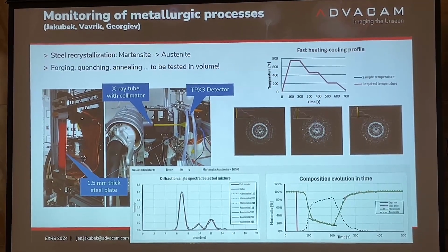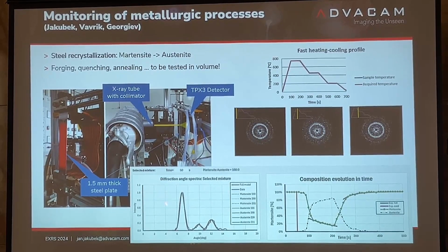One can prepare a very solid model for it, and here I am showing what happens. You know, this spectrum here. These are angles and intensity. These are peaks typical for martensite structure. Martensite is this one for low temperature, and there is always a blue line and a red line. The red line is the model, the blue line is the reality, the measured reality. It fits perfectly, and as you are heating it up, you start to see a big change.